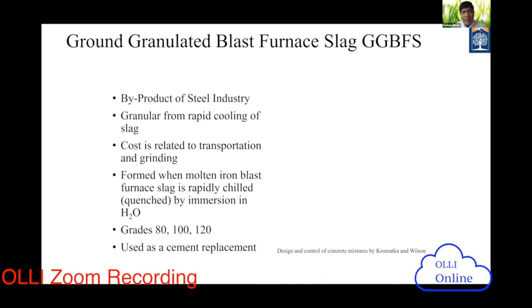And it has three different categories. I mean, three grades we are talking about: grade 80, 100, and 120. So, different grades, different activity levels. Obviously, 120 is the more active slag, 100 is the moderate, and 80 is the minimally active slag. Its cost is related to, again, transportation and grinding, how much finer material we are getting. So slag is also kind of more towards cementitious.